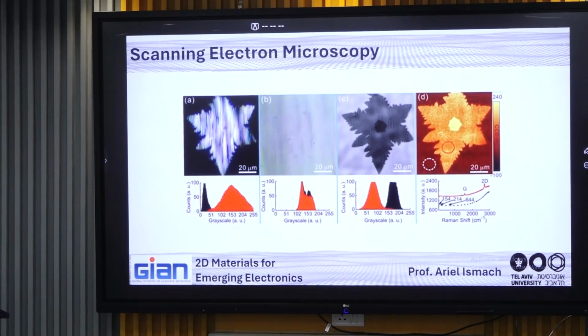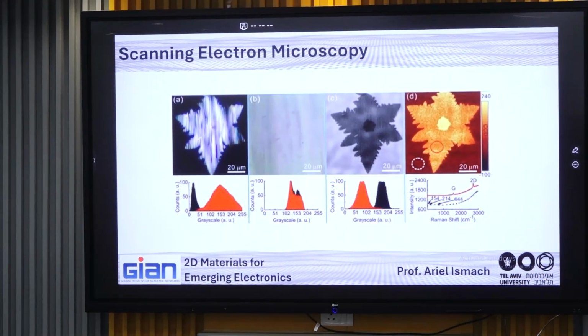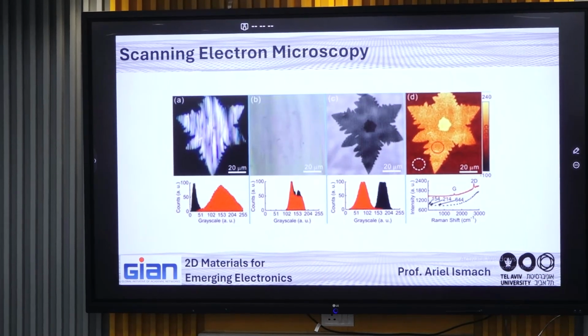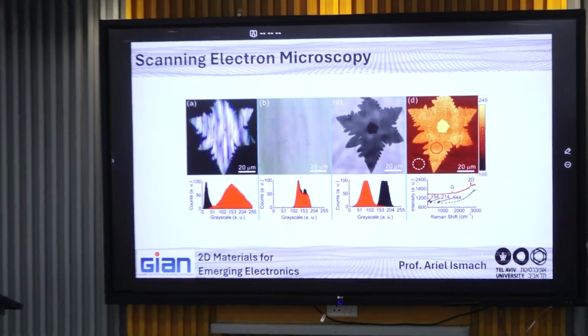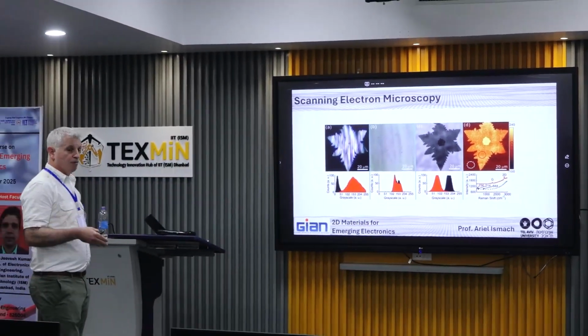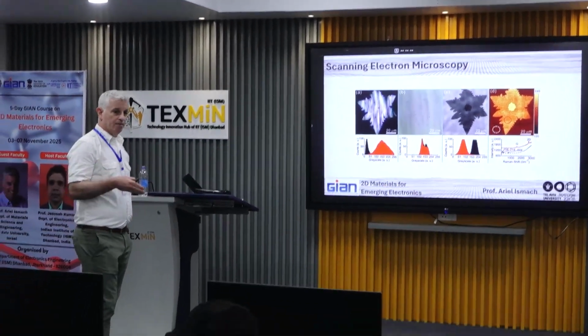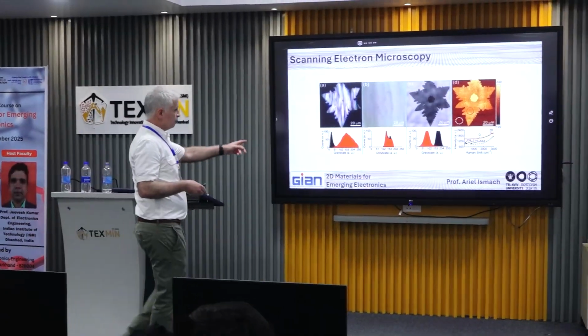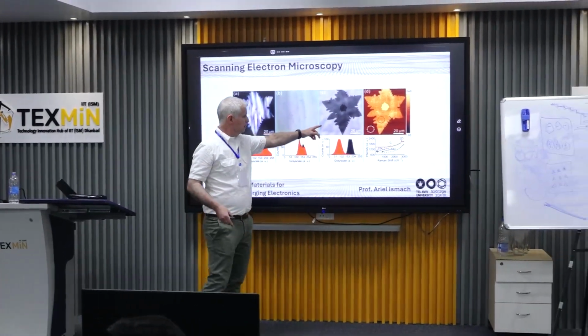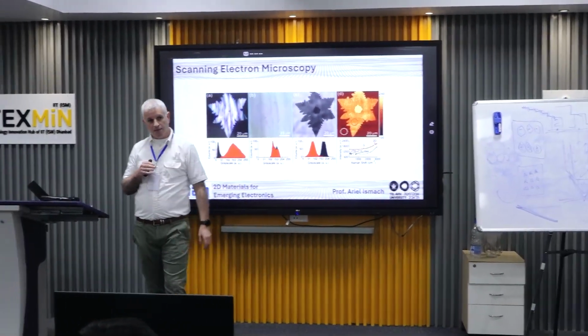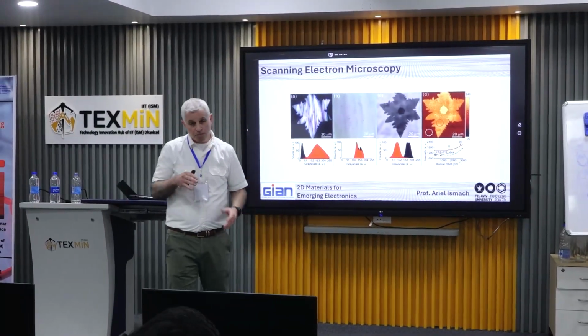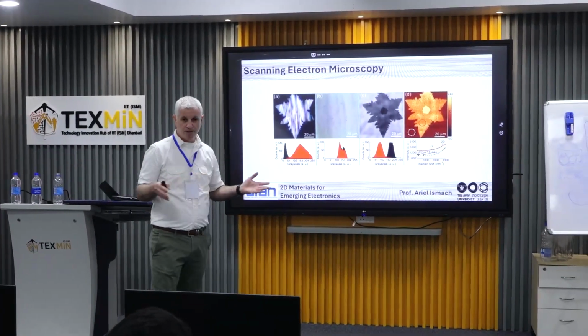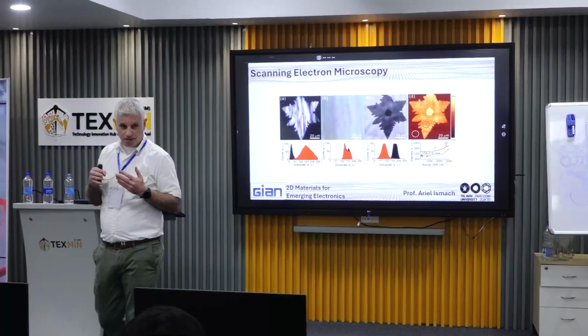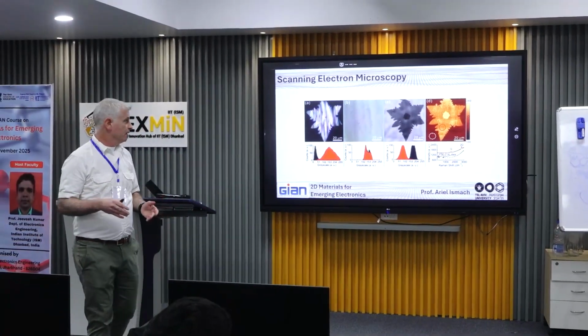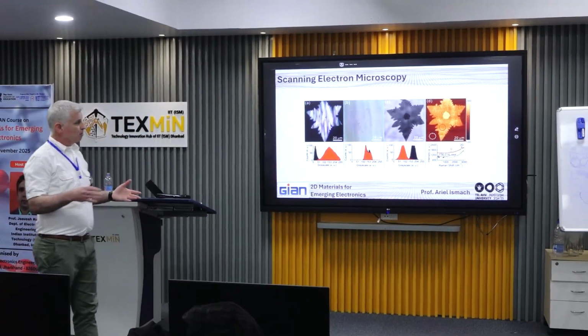SEM gives you another piece of information, but that's it. And the Raman gives you the proof that you have a single layer. By the way, not here and not here, you can't be sure that you have a single layer, most probably, because this is how the graphene works. This is not a proof that you have a single layer. So the Raman can give you all together.